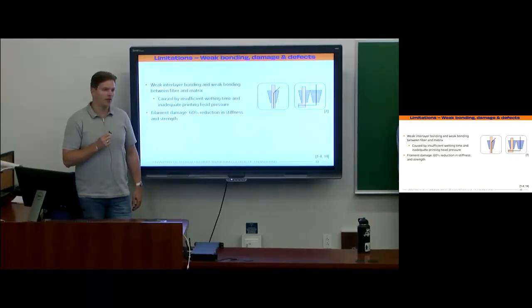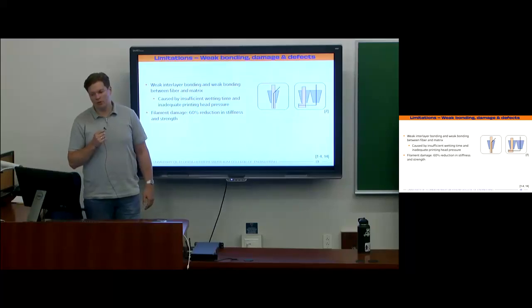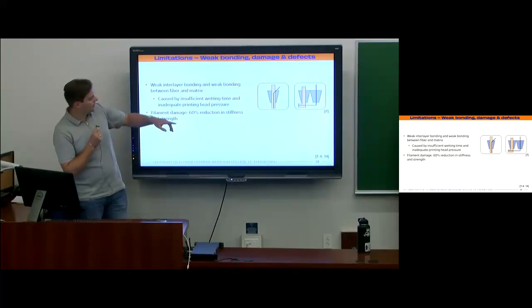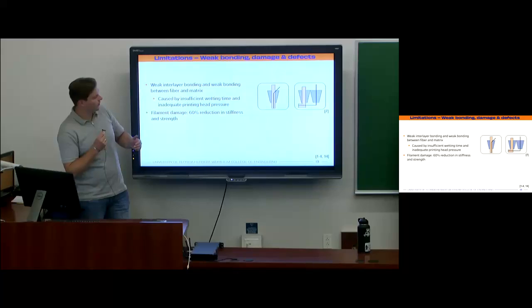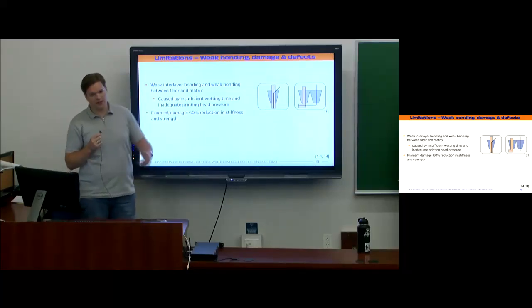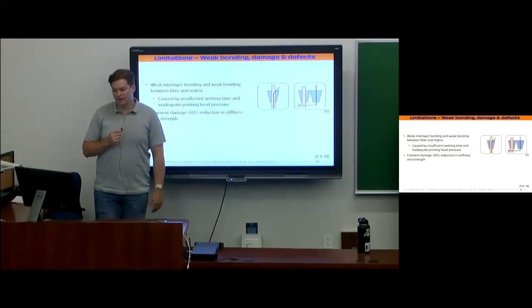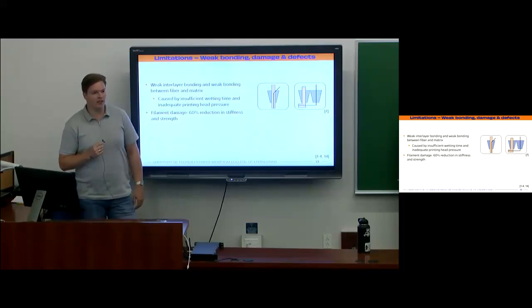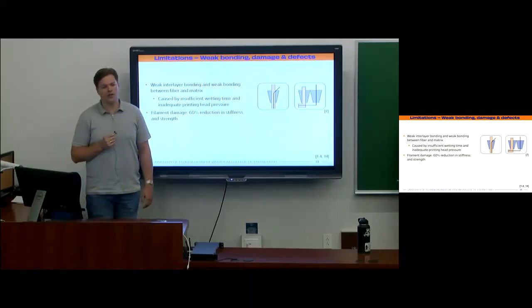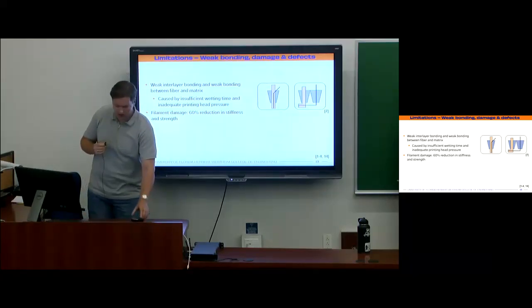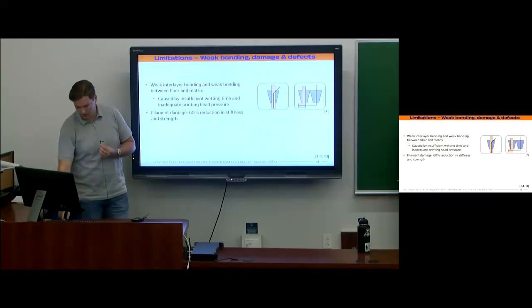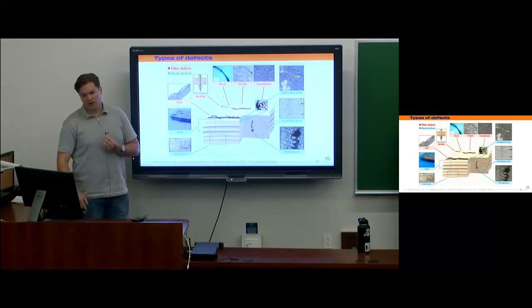And damage of the fiber filaments is also a big problem, because as shown in the figure, the filament or the fiber is bent by 90 degrees as it's being deposited, and that leads to a reduction of 60% in stiffness and strength compared to the unprocessed fiber material. So the materials don't reach their full potential in this process, which leads to weaker mechanical properties compared to traditional methods. And yeah, defects are a big problem.